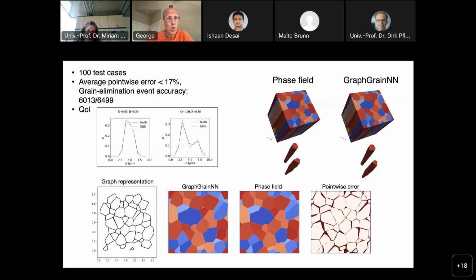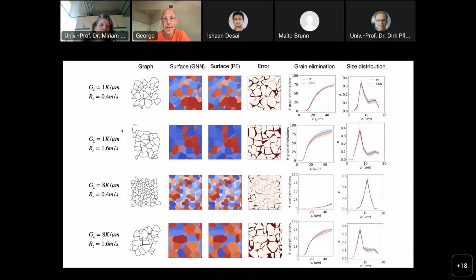This is a simulation in which we show how many grains disappeared, about 6,000. The actual value is about 6,500, and we predicted 6,000 elimination events. These are the quantities of interest, the statistics of the grain orientation between phase field simulations and grain NN, for different temperature regimes and melt pool size regimes. That's the phase field, and that's the graph grain NN distribution. And you can see these are different melt pool sizes essentially. The graphs look different depending on the condition.